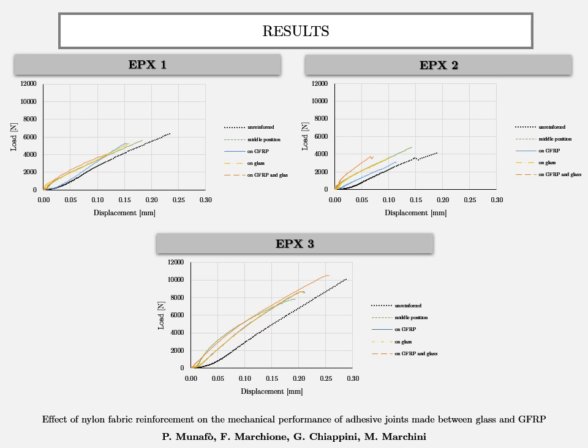The reduction in ultimate load is due to the interposition of nylon, which has lower strength than the pure adhesive layer. The nylon reinforced configuration in the middle position provides the worst mechanical performance and shows a lower ultimate load value of minus 33% compared to the unreinforced configuration.